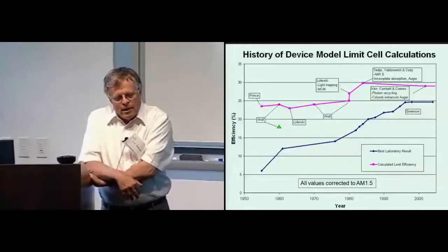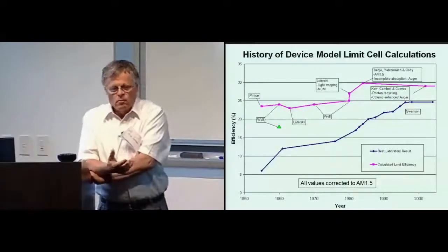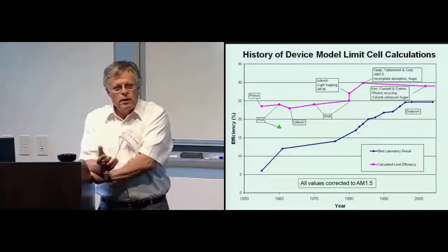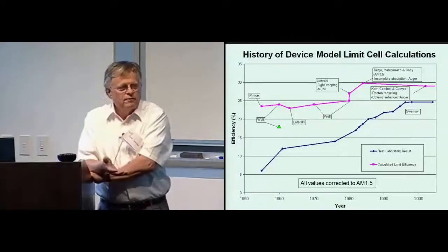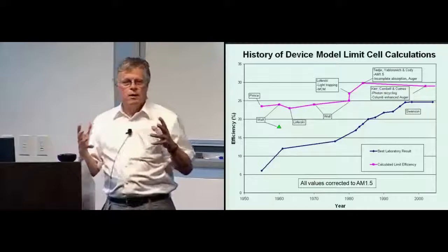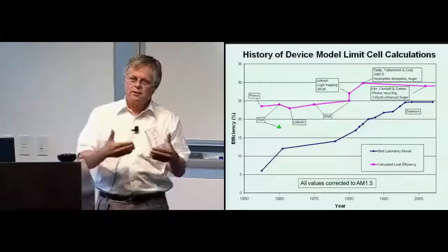And if you took the classic semiconductor device equations and say, well, that's all coming from Shockley-Read-Hall type recombination, why don't we eliminate all the defects and make it infinite? Then the equations blow up and you get infinite efficiency. But that can't happen. You have to have radiative recombination. The reverse of the radiative absorption within the cell has to exist.